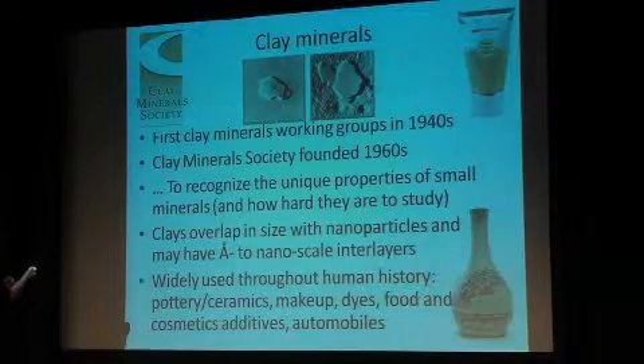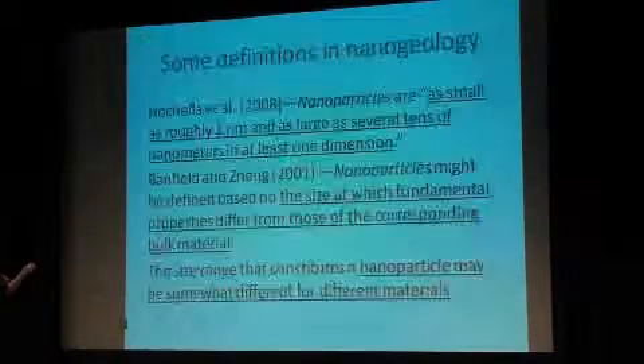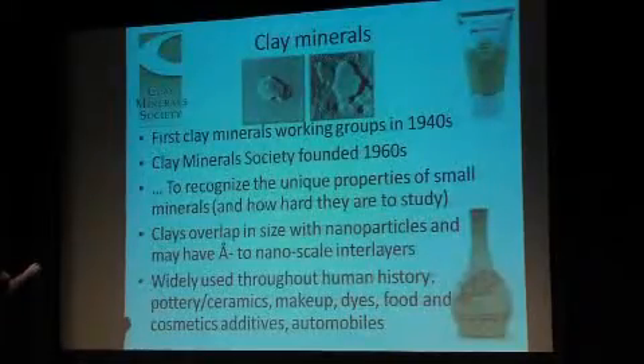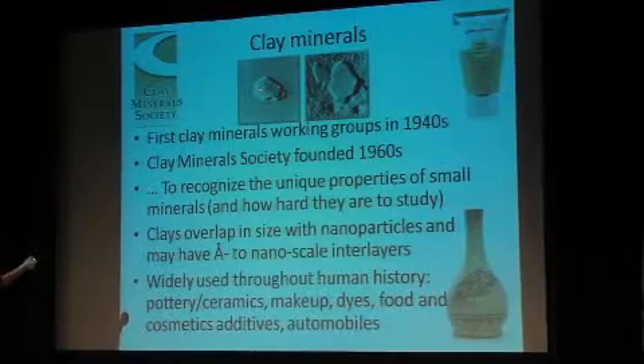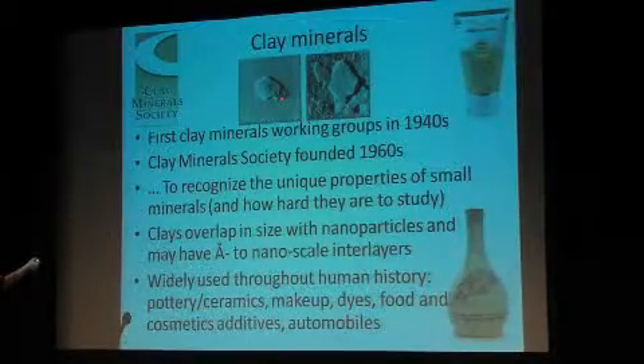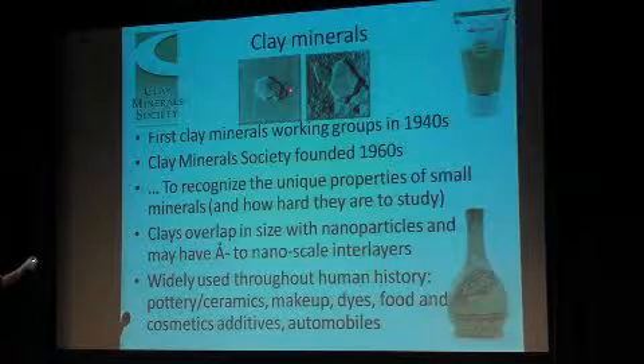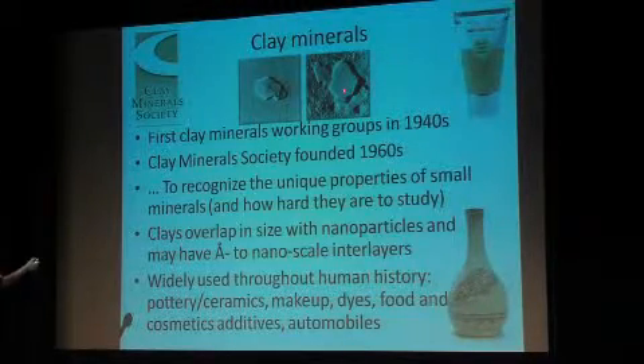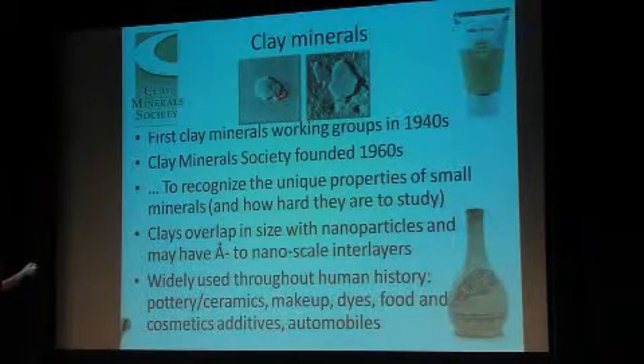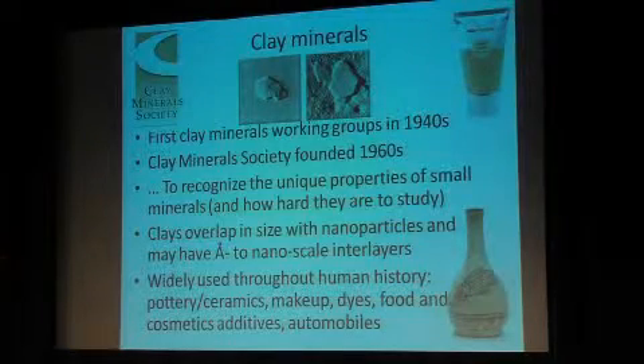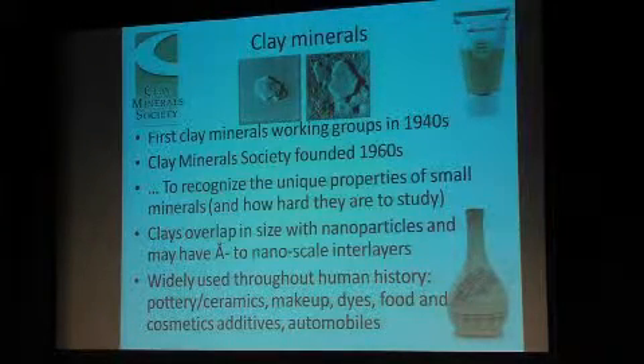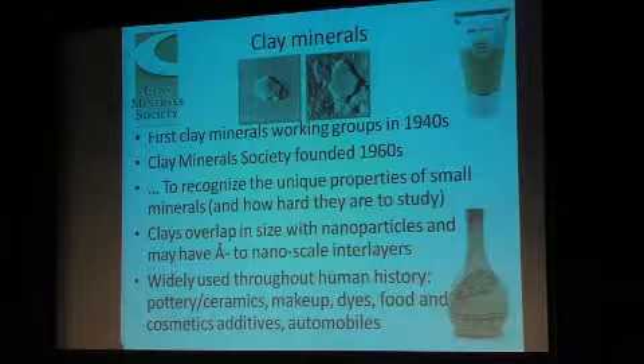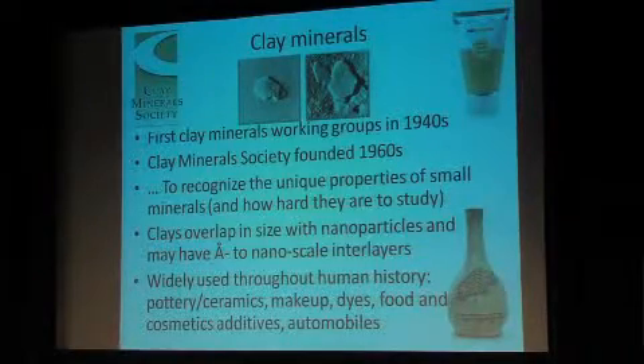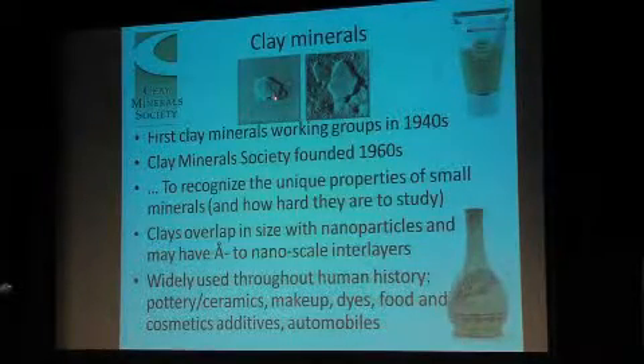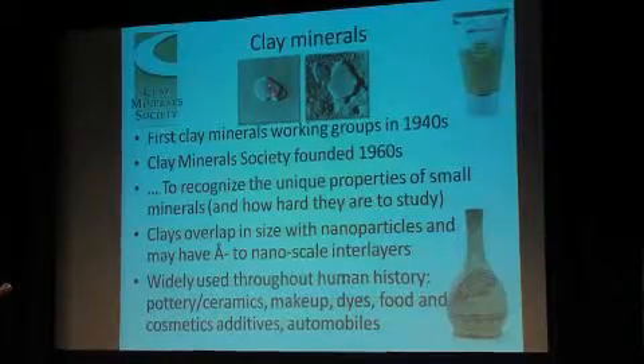This is kaolinite clay up here, for example. This one's about 300 nanometers across. There's another particle here that's probably about 100 nanometers. This one here is about 700 nanometers across. And you can get down a broad size range that scales the nanoscale and on up. Usually they tend to be quite thin, which definitely makes them nanoscale in terms of their thickness. And I want to point out they can have all sorts of features on them, like, for example, these steps I'm going to talk about later on.